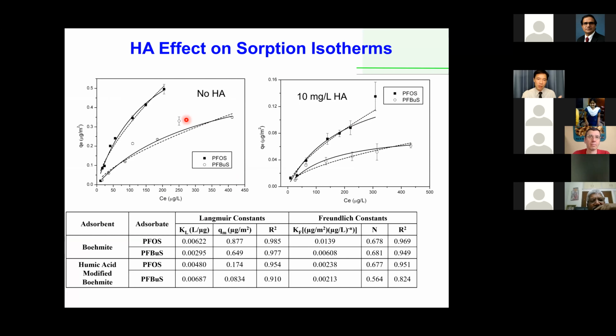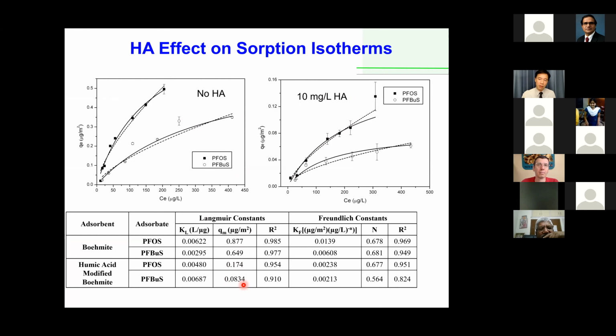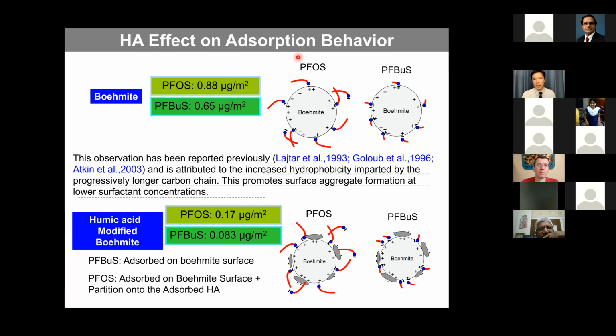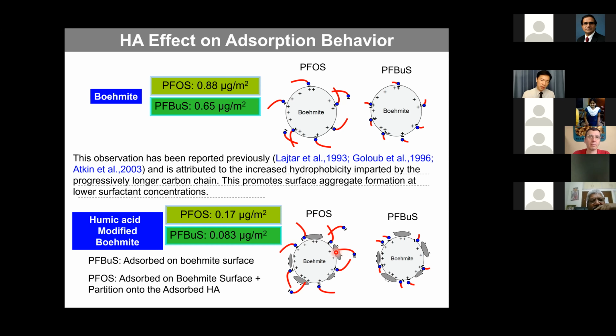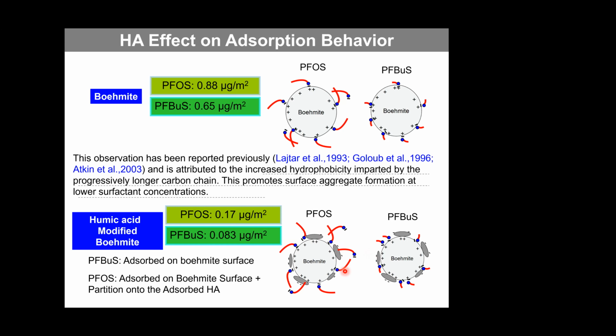We found out, very interestingly, that humic acid, compared to without humic acid, will in fact reduce the adsorption of this kind of pollutant, particularly with the different chain lengths. Because when you have the PFOS and PFBS, which are relatively shorter chain compounds, you have the electrostatic capability, and that makes these two types of compounds stay on the surface of the mineral. If you have the humic acid on the surface, you might have the PFOS take a little bit more advantage of this hydrophobic end to be attracted by the humic acid. But in fact, you reduce a lot of electrostatic interaction, and overall the adsorption capability will be reduced.